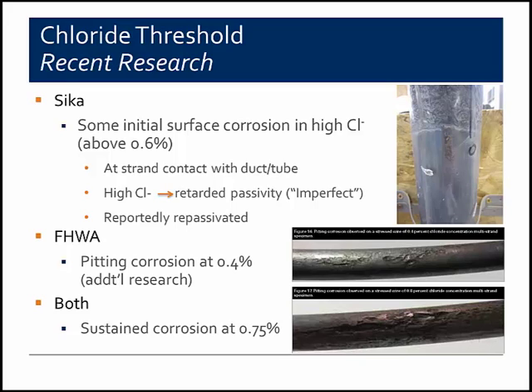Now, continued monitoring showed that this initial corrosion went dormant, and that region of the strand and the strand in general then repassivated. It was just a process that was retarded, particularly in that area where the strand was in contact with the tube. Federal Highway found some levels of pitting corrosion at lower chloride contents, as low as 0.4%. However, they noted that additional research was needed. It was not clear that that corrosion was sustained, and it may have been more of an initial corrosion phenomenon, somewhat similar to what Sika had observed in their testing. However, both researchers have reported that sustained corrosion occurred when the chloride content was at 0.75% or above.